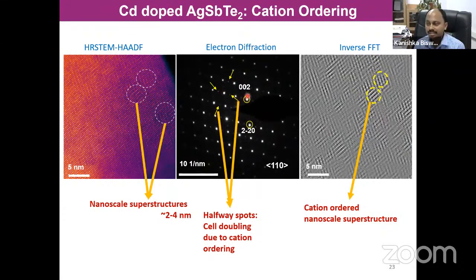I don't know if it's visible in these slides or not properly to the audience, but you can see very, very weak halfway spots. The halfway spots means basically there is a cell doubling happening. As soon as I dope cadmium, silver and antimony is ordered in this compound, and cell doubling is happening, and cell doubling is creating this ordering.